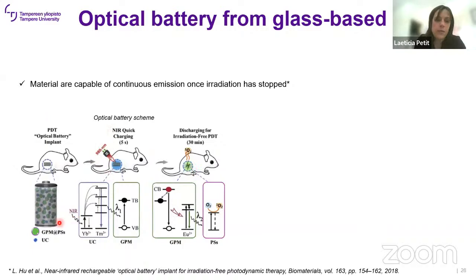So what is happening is, when you inject them in rats, you use the 980 nanometer excitation. This is absorbed by the ytterbium. Ytterbium gives the energy to the thulium. Thulium emits blue light. The blue light is absorbed by the persistent luminescent particle, which will charge or trap the electrons. As soon as you stop the radiation with the 980, you get this green persistent luminescence, and this leads to the photodynamic therapy.